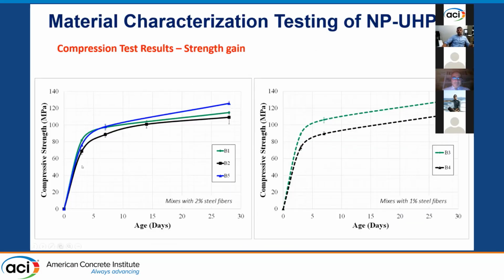So we did the compression test. These are some of the results here, for the strength gain. We are around the 120 megapascal, which is the 17-ish KSI that, again, is common for non-proprietary UHPC. And as I mentioned earlier, it's not a high-end 25 KSI type of UHPC. It's more like a practical low-end one for ABC joints. So this is the 5 different batches.